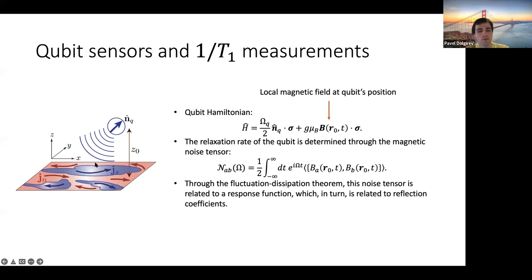So the setup is simple. We have a true two-dimensional sample. We have a spin impurity qubit here. What we imagine is that there is some kind of optical protocol that prepares initial state. So you imagine a spin that points in, say, upwards direction. Then inside the sample, there are thermal fluctuations of electric current. These thermal fluctuations, in turn, create fluctuations of magnetic field at the position of the qubit. So I think about Hamiltonian as if there is intrinsic splitting and external magnetic field that, in our case, comes from the sample. If we think about low enough temperatures, this is the only source for this spin to eventually decohere. And this decoherence time is what we say is one over T1 measurement.